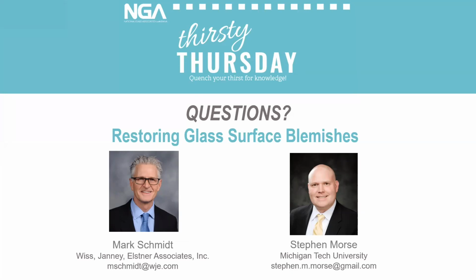Maybe we can tag team that one, Steve. Yeah, definitely. I have some opinions. A recent project we were on, we just used the ASTM C1036 criteria without a zebra board to try to detect distortion. In that case, we were looking through the glass in transmission out at some other buildings that did have some linear features that would allow you to identify any distortion. That's typically what we use. We're thinking about using a zebra board on an upcoming project in the Midwest after glass polishing. However, that's the criteria that we've been sticking with, what's available in the C1036 standard.